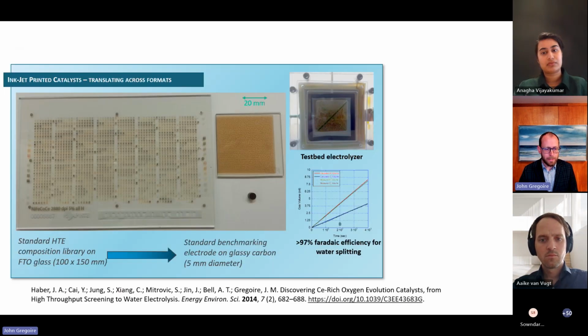But for the data I'll focus on in the area of electrocatalysis, we printed these libraries as I described before. Whenever we get a hit, a catalyst that looks interesting in that library, we can take the same ink formulation and print a larger version. So we could go into a test bed electrolyzer and did a lot of validation of the high throughput techniques using this type of approach. We also print on rotating disk electrodes to perform more traditional and trustworthy electrochemistry, which was really critical in validating all of our techniques to get this high throughput.